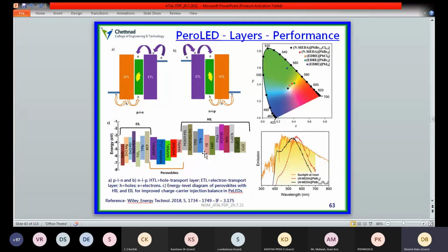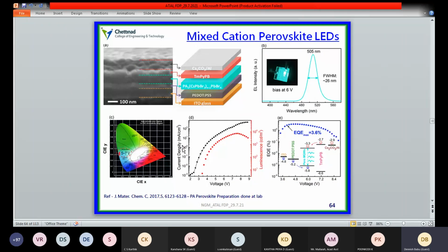It is mentioned that there are very few literature reports available on cesium-based perovskites, especially metal halide based perovskite research work, which is very limited. That motivated us to work on these perovskite-based devices for LEDs. We have prepared a phenyl ammonium with cesium lead bromide based perovskite with the help of a hot injection method, and we have fabricated one LED device.